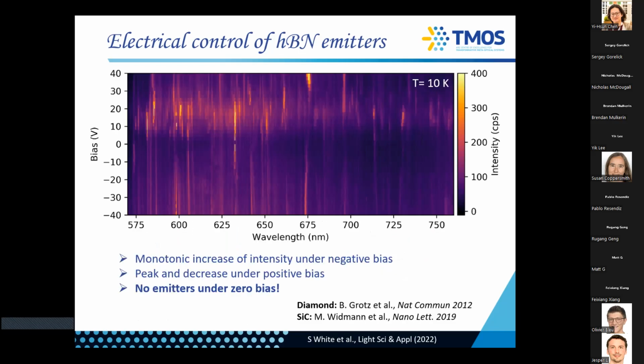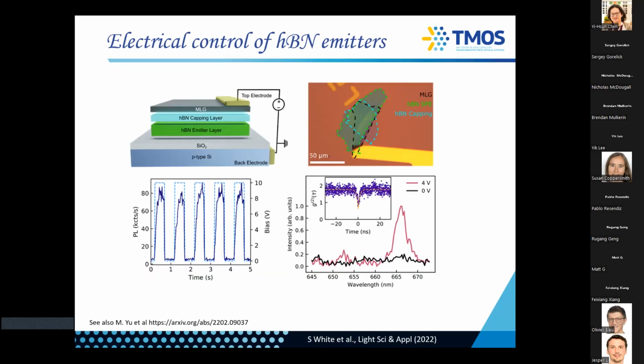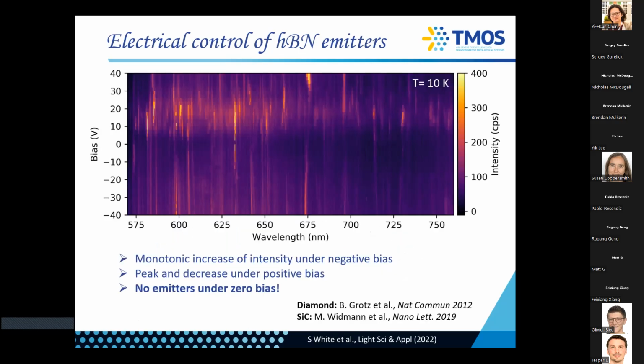So what is happening? For this, we took an hBN with a very high density of emitters, and what you see here is basically a spectral map of many different emitters. So every line here is a single photon source. It's all done at 10 Kelvin, so the lines are very narrow, a few nanometers, and you can see what's happening. So at zero bias, there is almost no emission, which is here. As you increase the bias, let's say you go to 10 volts, you start seeing some emitters, and then as you increase the bias more, they all disappear. And that's reproducible. So let's say this emitter turns on at about 20 volts, this emitter turns on at about 30 volts, etc. So every emitter turns on at a random voltage and then goes off.